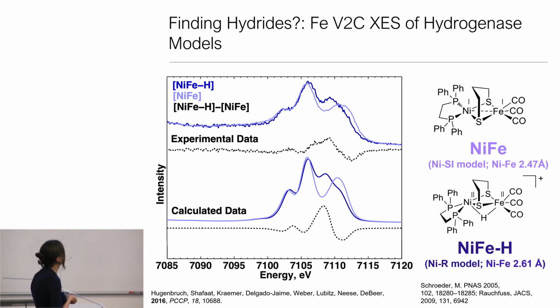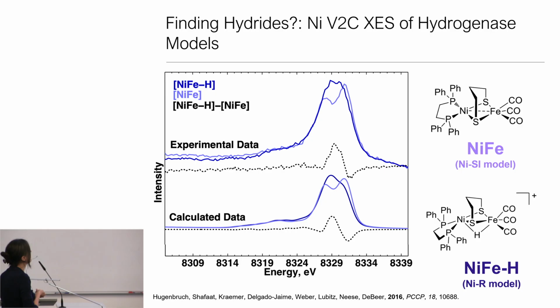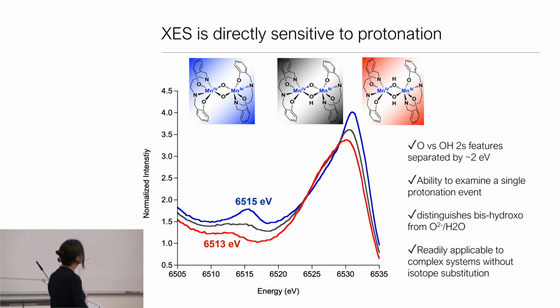And so that's what you're actually seeing here in these iron spectra of these nickel iron models, where you have the hydride present in the darker spectrum, and that's what gives rise to increased intensity in the experimental data, but also in the calculated data. And we can also look at it from both perspectives, see that it is clearly interacting with the iron, but it's also clearly interacting with the nickel, and it's present there in both experiment and theory. And so this just gives you an idea of how this works.